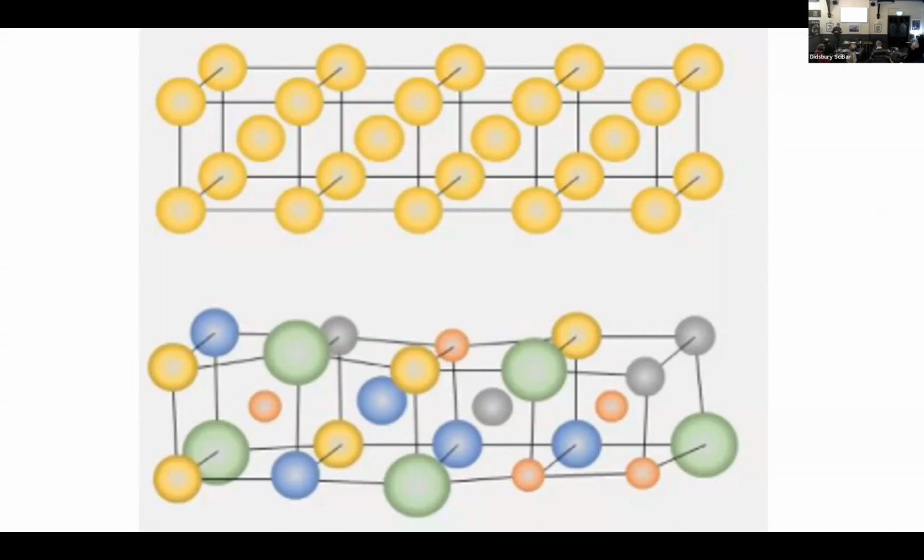Essentially, to give you a flavor of some of the new materials that we're looking at, some newer than others. One concept is multi-component alloys. So instead of having your steel, which is 95% iron, your zirconium rods, which are 95+% zirconium, we make a stew. We take a bit of this, bit of that, bit of everything, mix it all together, and we form a crystal structure that is now wibbly wobbly because we've now put atoms of different sizes into it.